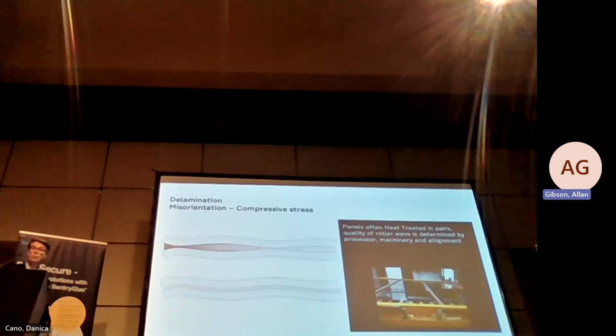When dealing with interlayers with a gauge of 0.76 millimeters, for instance, with a tolerance of 0.5 millimeters, there is a high risk that all that void will not be filled, especially during the processing where you're squeezing the plies of glass together under heat to extract as much of the air as possible. It will apply pressure, and then it'll be autoclaved. But should this occur, then over time, when the material is installed with thermal movement of expansion and contraction, it can open up and prise open the glass and reveal the laminated glass, and an air pocket or failure can occur as a result of that.